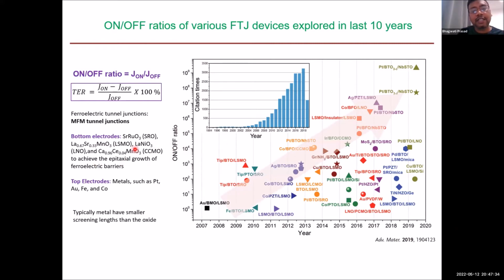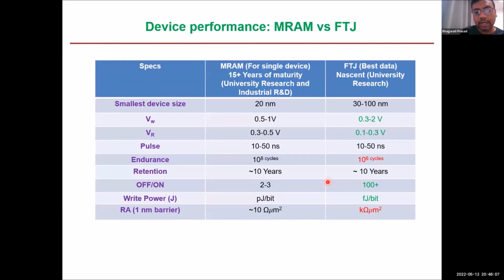Typically, people use the bottom electrode as an oxide. You see that they have used SRO, LSMO, lanthanum nickelate, and many other oxide systems, and then they use a top electrode such as platinum, gold, iron, or cobalt, because the metal has a smaller screening length than the oxide. So you see a large screening length difference between the two electrodes, and as a result you see a big on to off ratio, because you get well separated barrier heights for the two directions of ferroelectric polarization.